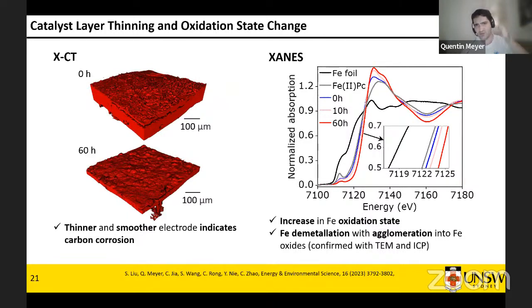So operando measurement, we tried to do operando measurement. What we did here is we scanned a catalyst layer at the beginning, and then we scanned a catalyst layer after 60 hours of operation. The first thing we can see is the electrode is way thinner after 60 hours. That's one thing. Second one, it's also much smoother if you look at the surface. So when you have a carbon-based material and you lose a lot of thickness and it looks smoother, typically what this indicates is carbon corrosion. We carried out some more advanced characterization using XPS and Raman, and we've confirmed indeed we have carbon functional groups and carbon corrosion taking place.